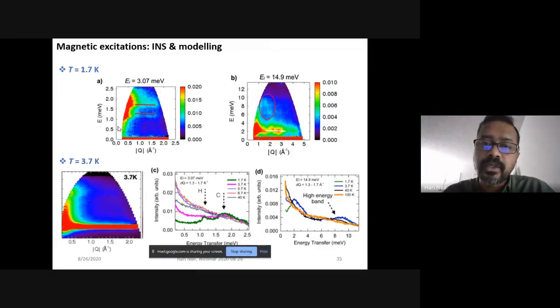When you increase the energy, they sort of merge into one line, and that's the white line on the image panel B. So at around 2 meV, you can see that there is a white line, and that's the excitation that we are talking about. It sort of merges into one.